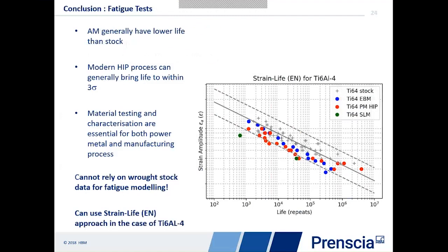So in conclusion then, when we look at fatigue tests, I think you'll agree that even with hipping and things like that, additive manufactured components and powder metal materials generally have a lower life than the original stock material. However, modern HIP processing can generally bring the life to within 3 sigma, and that means that it becomes practical for real structural applications.